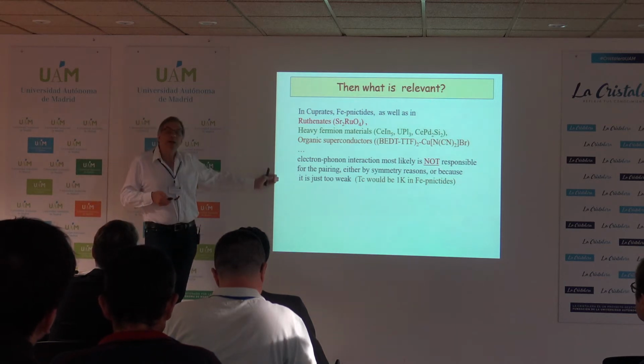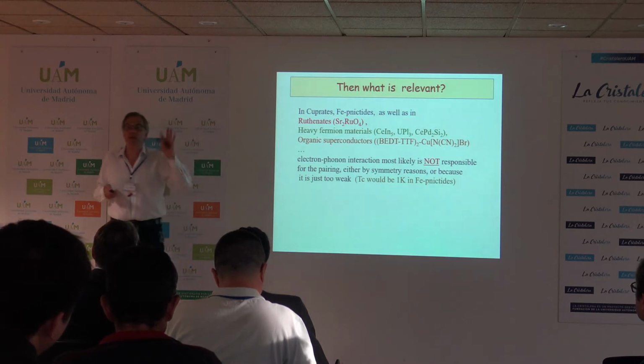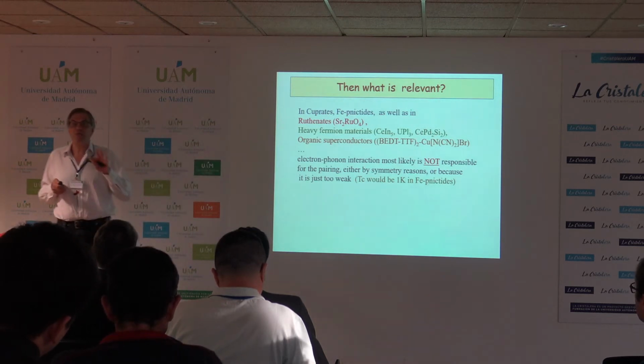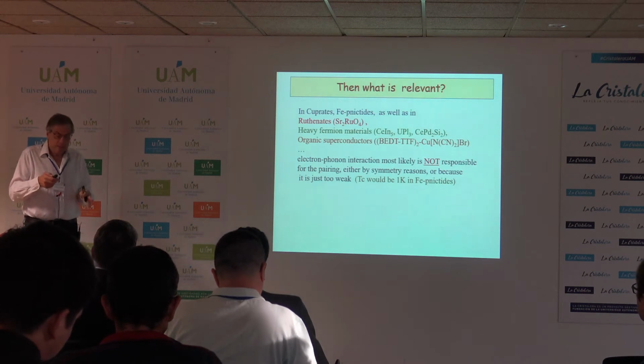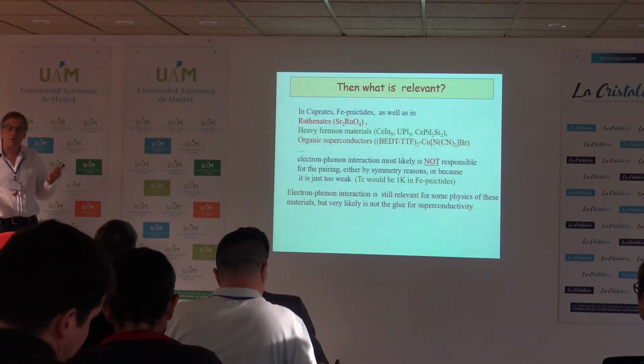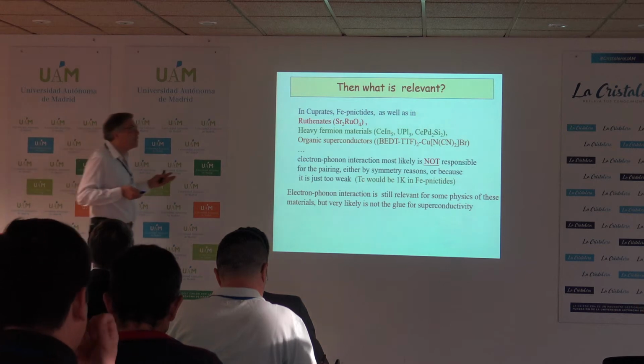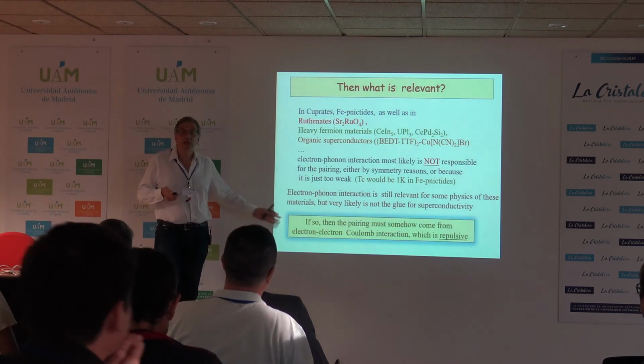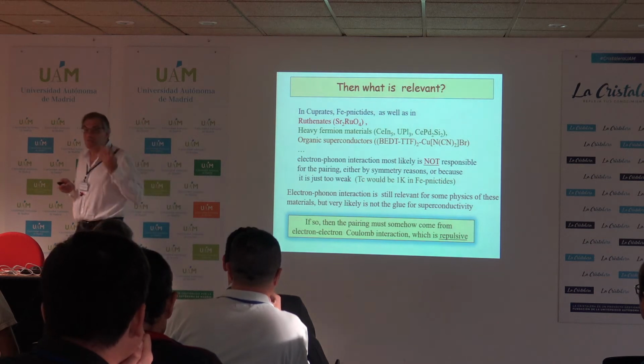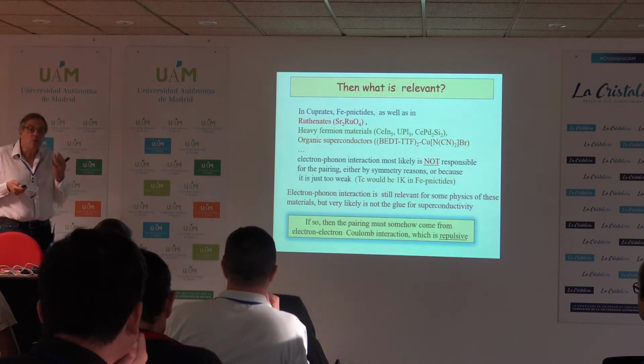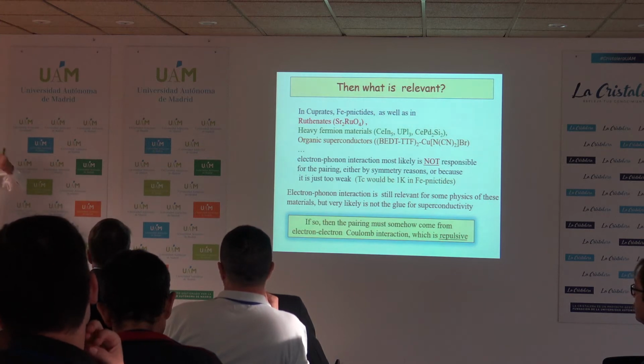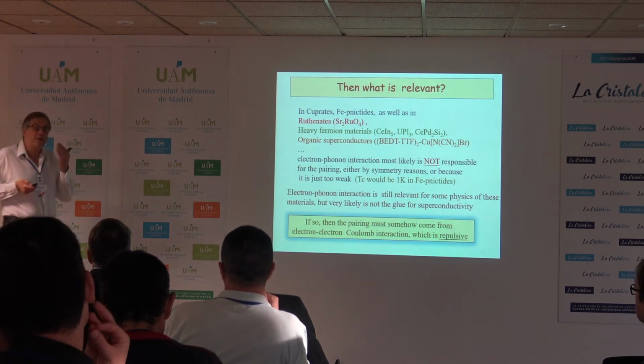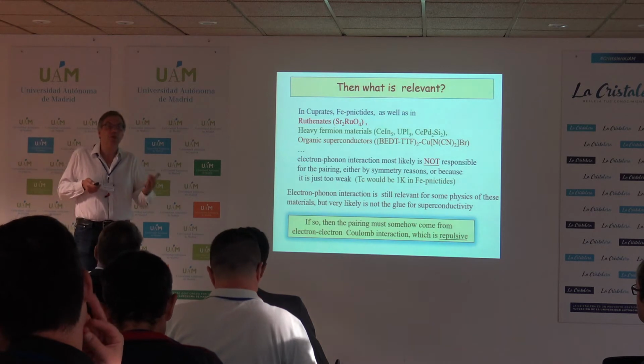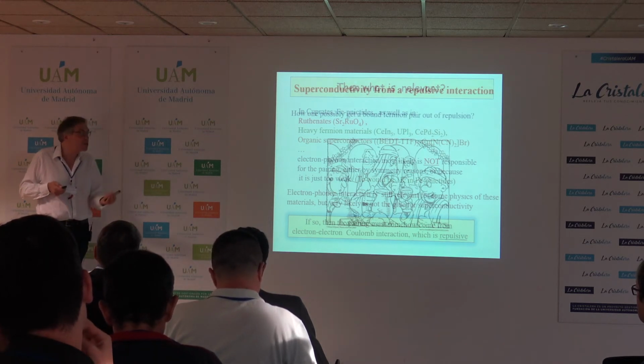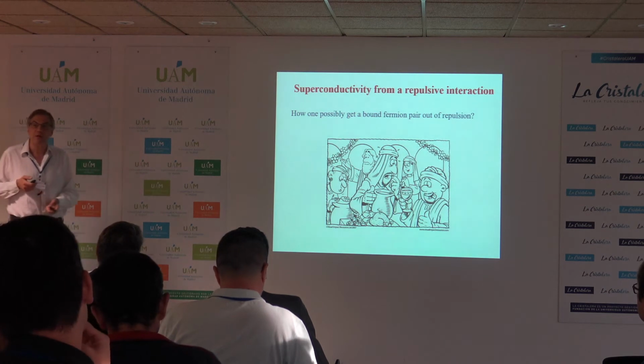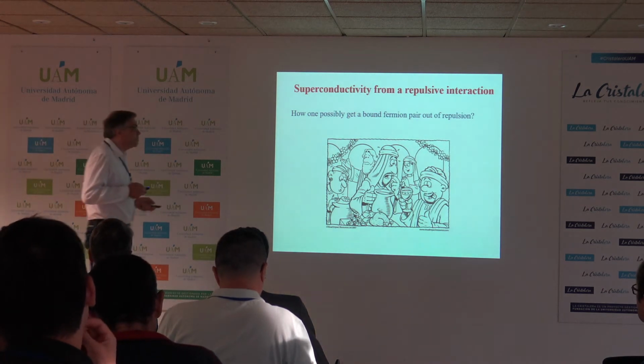So if, by purely looking at symmetry and at the numbers, electron-phonon interaction seems to be incapable, then this brings us to the subject of this school: what is left? Then there is not much left. It should be electron-electron interaction, which is repulsive interaction. So then the question one can ask as a zero-order question is how one can get a bound state of two fermions out of nominally repulsive interaction. And this brings me to the issue of how to get superconductivity out of repulsion.